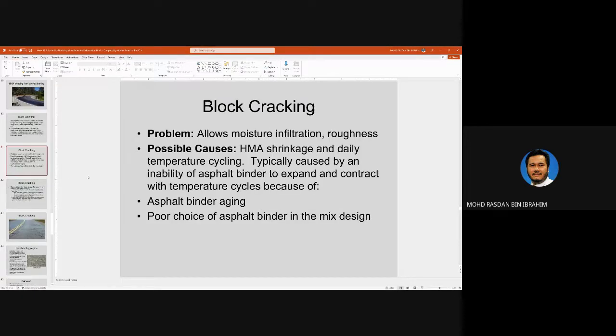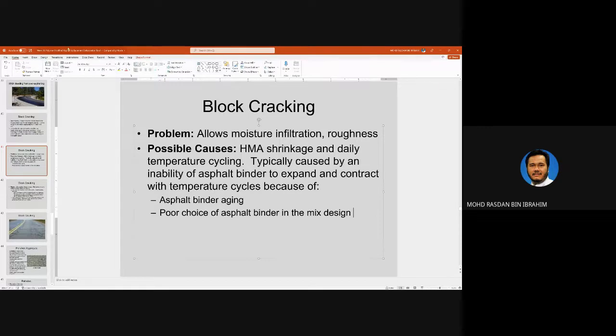So the problem is it allows moisture infiltration and roughness. It is caused by HMA shrinkage and daily temperature cycling. That's why if you see in movies, particularly in the colder regions in the US, they usually have cracks, and the cracks have been sealed with bitumen. So this is caused by daily temperature cycling. Typically caused by an inability of the asphalt binder to expand and contract with temperature cycles because of aging, and also poor choice of asphalt binder in the mix design.